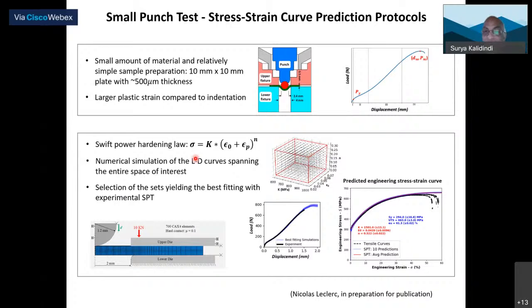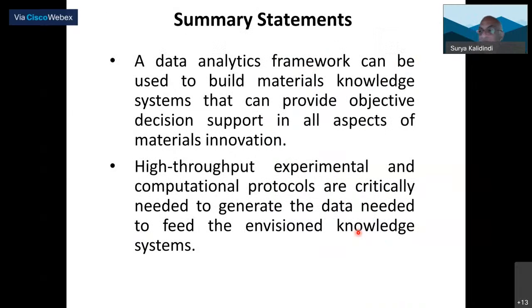So for that, we again do the same thing. In this case, the physics-based model is still a finite element model. So we do a finite element model with a lot of different physics, plasticity physics, and we create a database, we create a knowledge system. And then when you do the actual experiment, you have the experimental curve. We are able to come back and say, yeah, based on that experiment, the tensile stress strain curve or uniaxial stress strain curve for that material looks like that. And again, the purple is the prediction, the black lines are the real experiments for a particular sample. So you can see that the same methodology works even for SPT. So with that, I think I'm going to stop here and take questions.